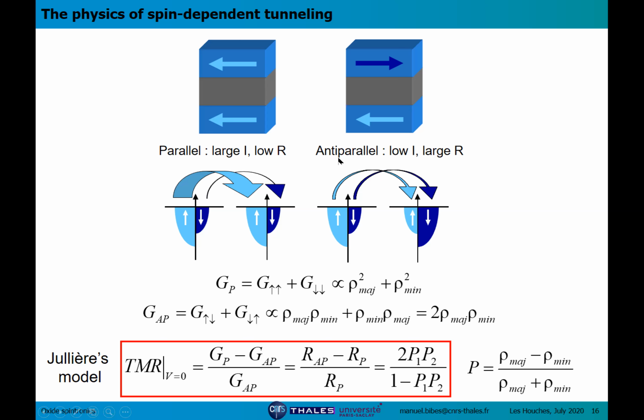If you reverse the magnetization of one of the ferromagnets, you reach the anti-parallel state, and then you will have moderate currents carried by spin up and spin down. So overall, you will have a lower current and a larger resistance. This explains the tunnel magnetoresistance effect. You can relate the amplitude of the conductance in the parallel state and in the anti-parallel state to the density of states of the ferromagnets. And you can arrive at this expression, which is called the Jullière formula, which was included in the first paper of 1975 of Jullière.